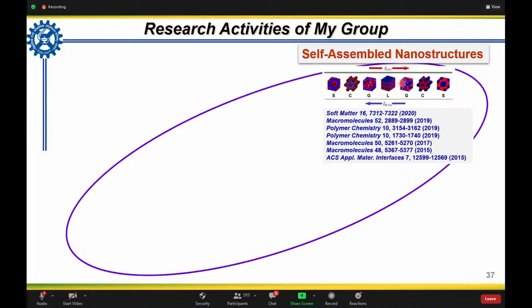So here you can have different kinds of morphologies, but this is mainly applicable for simple amorphous diblock copolymer systems. In our case, we are interested in such systems also for generating nanoporous membranes or templates for different nanofabrication. Apart from that, we are also introducing semi-crystalline polymers into these systems. Then there will be a complexity, a competition between the crystallization and microphase separation. So our group is interested in understanding the morphology formation using different scattering techniques.